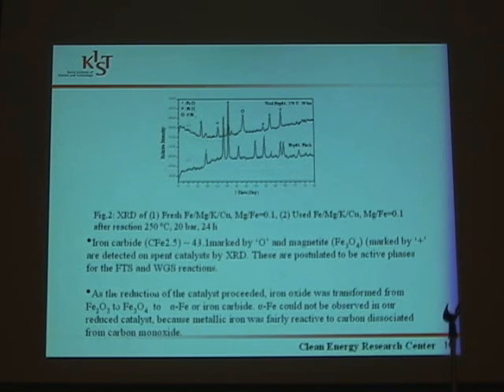This sample shows the comparison of the fresh magnesium promoted precipitated iron catalyst, having a magnesium to iron ratio of 0.1 by atomic ratio, and second is the used catalyst, the same used catalyst after the reaction at 250 degrees, 20 bar for 24 hours. It is seen that iron carbide, it is CFe 2.5, around 43 here.